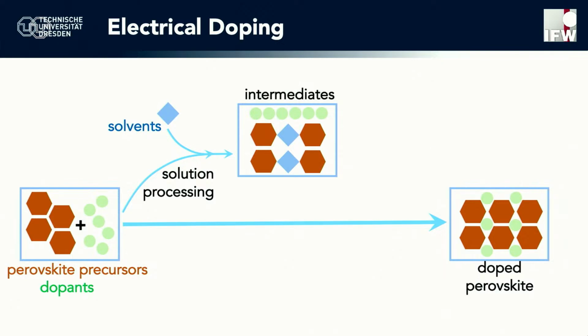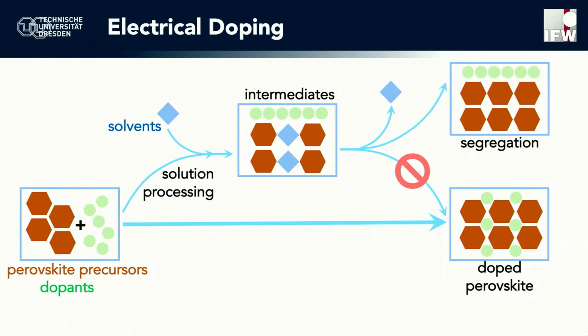And in perovskites, the solvents mediate the crystallization of the perovskite crystal, and by doing so, expel the dopants out of them. And so that means that when we then anneal the sample to remove the solvent, we don't actually end up in the doped perovskite structure we wanted, but most often we end up in a segregated case where only the surfaces and interfaces are modified.